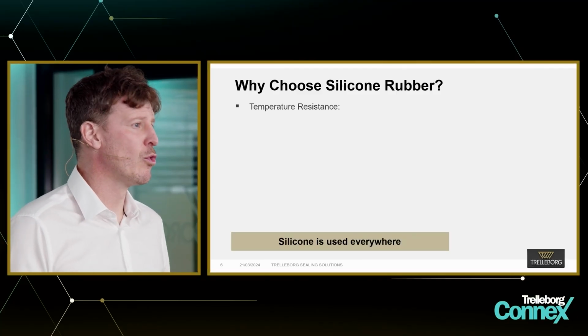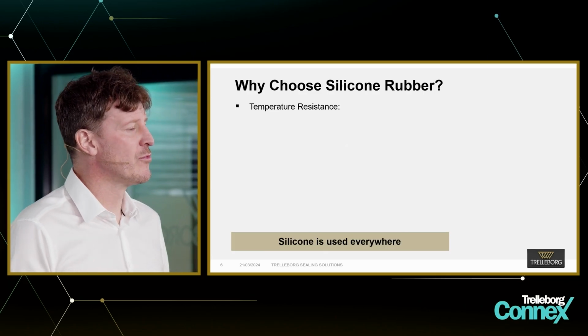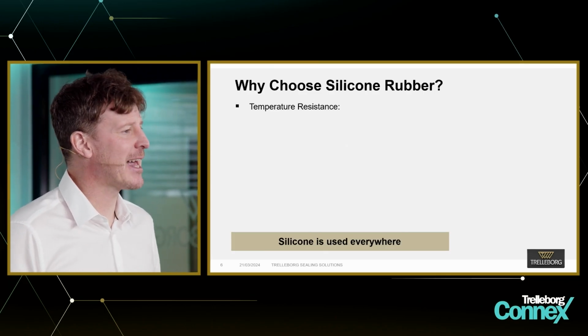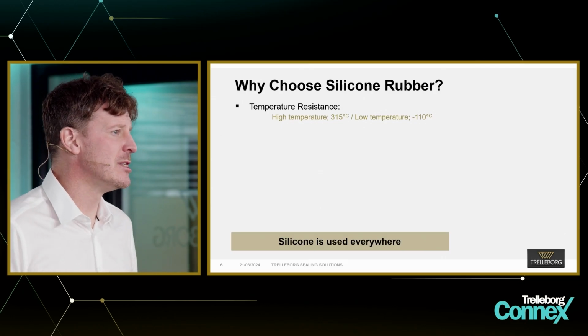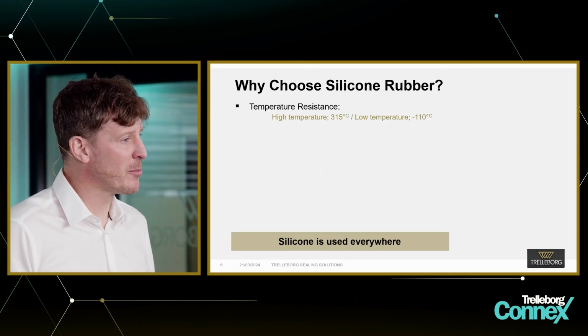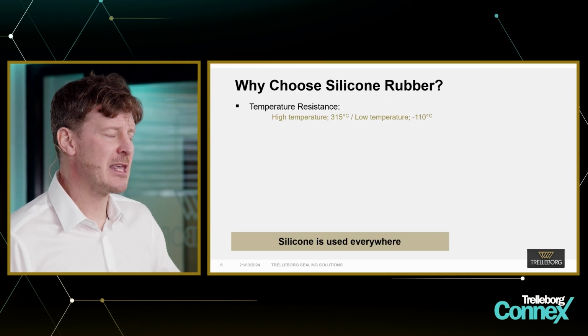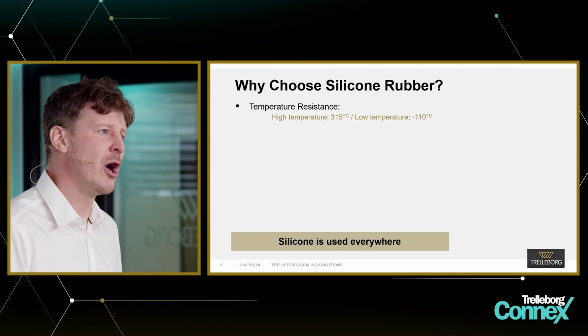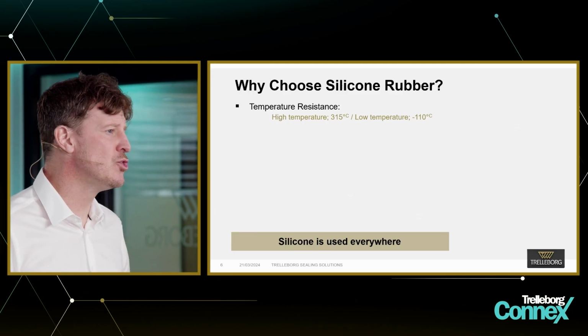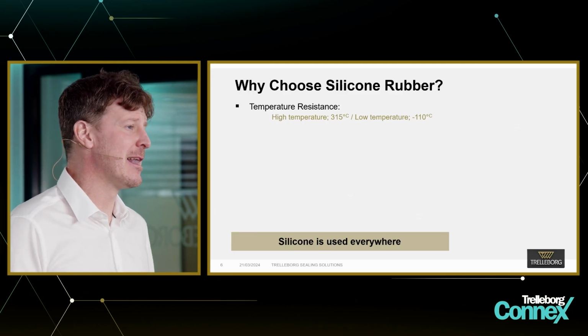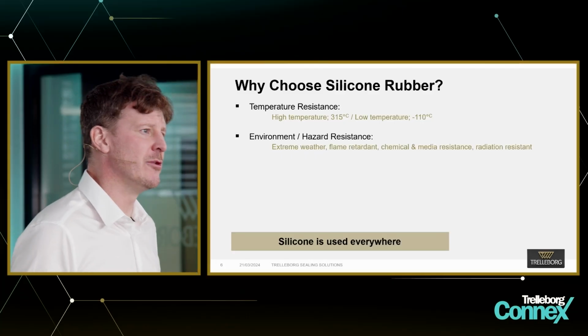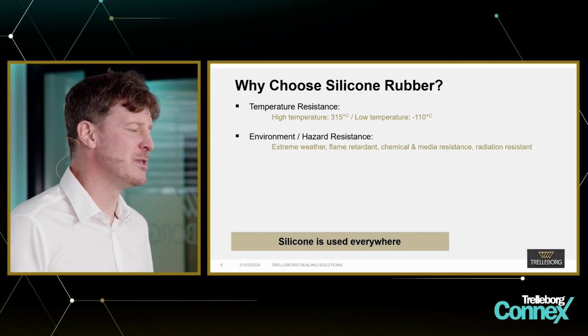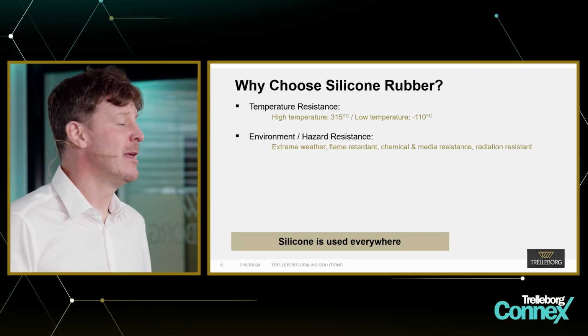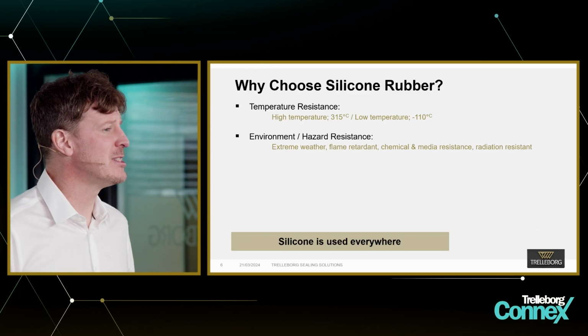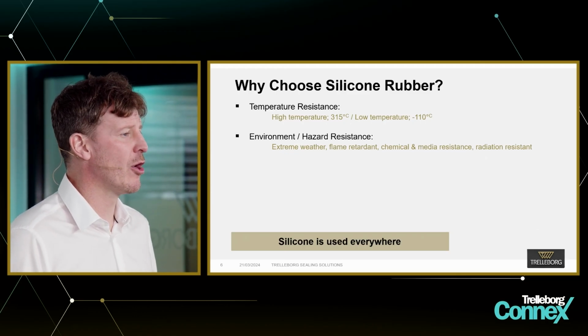Silicone is used everywhere, all around the world, in all different applications. One of the key benefits of the material is this outstanding temperature resistance. So silicone can see temperatures as high as 315 degrees, and in some cases higher for shorter periods of time. Conversely, it also remains flexible down at minus 110 degrees C. So this huge temperature range is not matched by any other elastomer at all. It has outstanding environmental and hazard resistance, extreme weather, flame retardants, chemical and media resistance. This can all be improved with specific additives and formulation improvements as well. It is a radiation-resistant material and can be sterilized via all forms: E-beam, gamma, ion, autoclave.